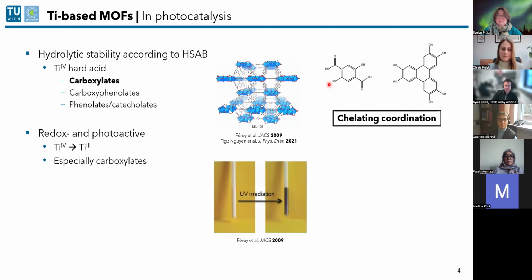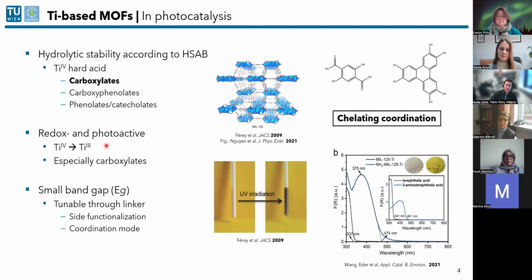What is also very interesting about titanium MOFs is their redox and photoactive behavior. So what I mean by that is when you illuminate titanium-based MOFs with light, you have a photo-assisted reduction of the titanium 4+ to titanium 3+. And this is especially observed in carboxylates, like it was first described by Férey. So this observation has been made since quite a while ago, and you see this color change due to this photoreduction.